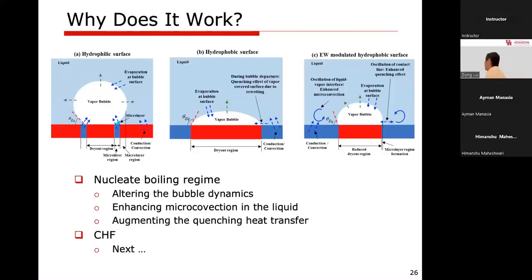So for the nucleate boiling regime, we have some more obvious answers, because there's an electrowetting force acting at the contact line of the bubble, so the bubble dynamics will be affected. So that will help to change the departure dynamics, therefore enhancing heat transfer. Also, because of the oscillation of the bubble interface, there's enhanced microconvection that will also help to increase the heat transfer. Now, the other mechanism is that when the contact line moves, because there you still have the pure liquid, it's a so-called transient conduction process. So the electrowetting actually will augment the quenching heat transfer. That again increases the heat transfer.